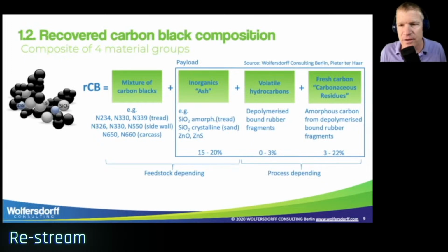Now we get two other groups of materials, and these come from the depolymerized rubber polymer. There could be volatiles, organic volatiles on the recovered carbon black. This is also not good because it doesn't pick up the opportunity of value creation of having a low PAH content. PAH are the polycyclic aromatic hydrocarbons, and you might know that first of all, the industry demands a very low content of PAH, but also the type of virgin carbon blacks that have low PAH content are much more expensive than the normal carbon blacks.